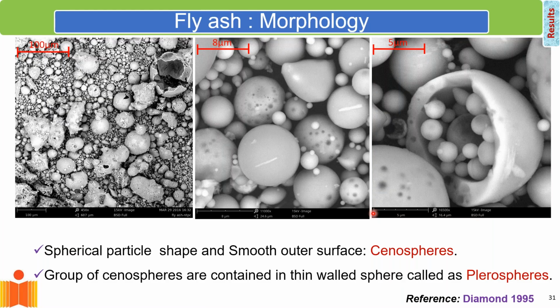So just to show you what fly ash looks like, if you look at fly ash under the microscope, it basically consists of all these spherical particles, and these spherical particles are basically glass. These spheres are called cenospheres, and they are primarily glass. The reactive content of fly ash is contained in these glass spheres. So when we're talking about fly ash, it is the glassy content in the cenospheres that we are interested in.